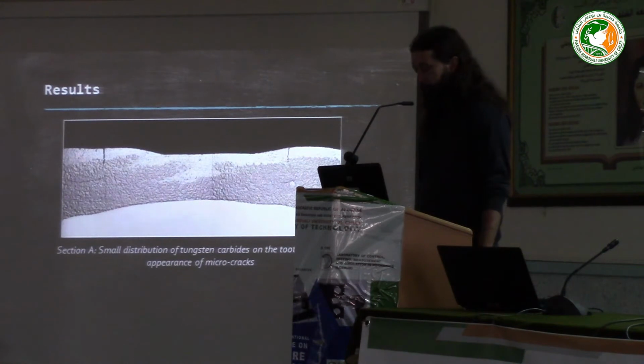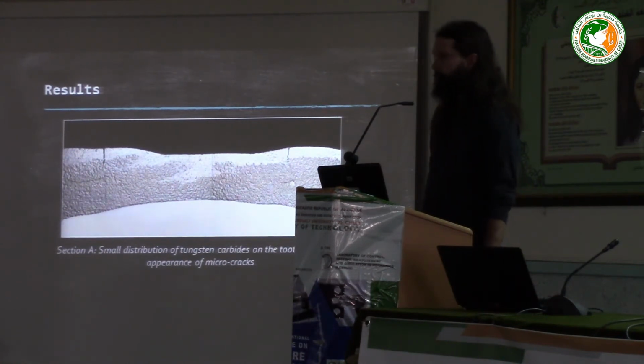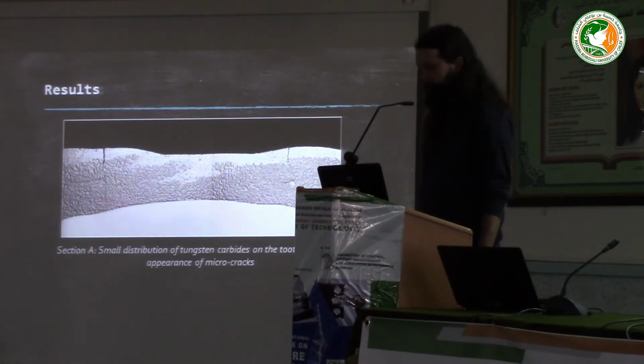So here we have the results for section A. This is the section on top where the thickness of the welded layer was the lowest, around 3 millimeters, and where the tungsten carbide content was also low. So here you can barely see any of that, but you can also see that there's only a few micro cracks in this particular section.